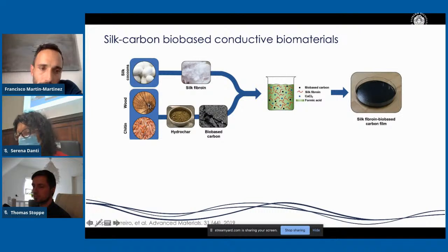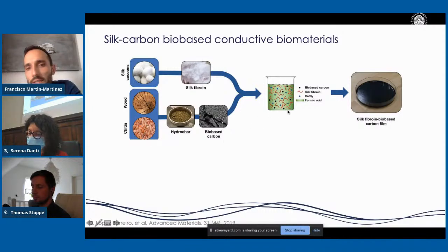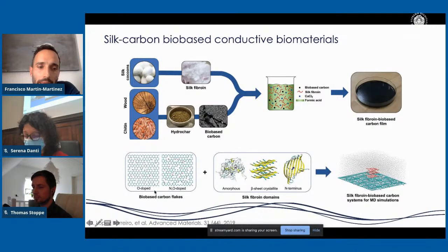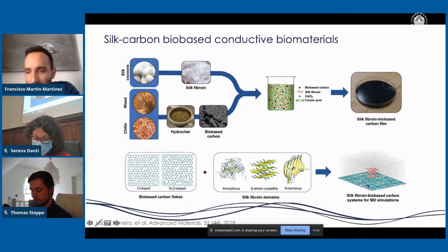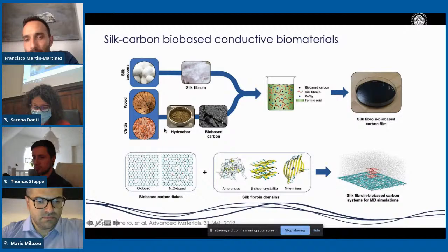So basically, we explore again wood-based carbons and chitin-based ones. When you put all these in the solution, we also add calcium chloride to control the humidity and water absorption of the membranes. We can produce these membranes of silk that have this bio-based carbon embedded. We also made simulations to look at how the silk fibroin domains attach to a surface of carbon with the functionalities that are coming from biomass.